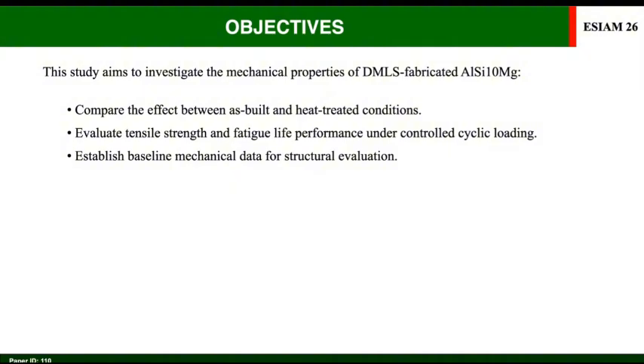First is to compare the effect between the as-built and the heat-treated condition of a specimen. Second, evaluate the tensile strength and the fatigue life performance under controlled cyclic loading. Last is to establish baseline mechanical data for structural evaluation, carried out by the configuration of an experimental work.